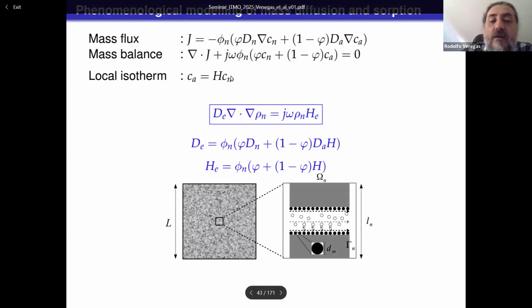We insert this equation here, and we can write all of this in terms of densities instead of concentration to get this equation, where D is an effective diffusion coefficient that has two components. One is weighted by this bar phi, which is the volume fraction available for transport of free molecules. One minus phi is the volume fraction available for the transport of adsorbed molecules. This diffusion coefficient is also multiplied by this H constant that is relating the concentrations. HE is called a linearized effective equilibrium constant, and appears multiplying the density profile in this equation.